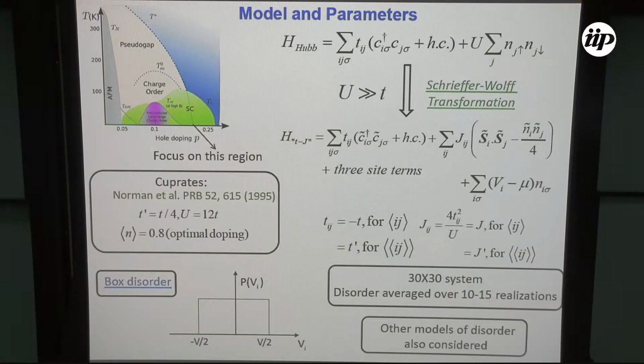So we started with a repulsive Hubbard model. As many of you know, for very large U, very much greater than t, you can do a Schrieffer-Wolff transformation, which takes care of the fact that you remove all double occupancies and virtual processes. You can land up with a t-J model, and then we introduce disorder in this problem. After deriving this t-J model, we introduce disorder like this, which is just an on-site chemical potential.